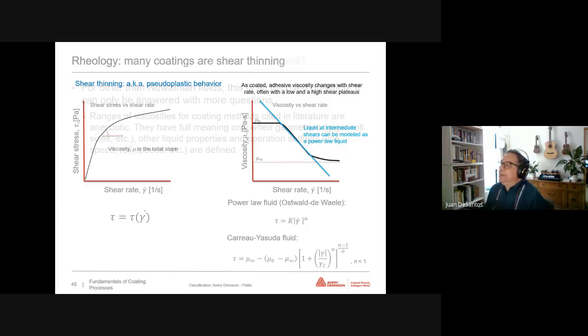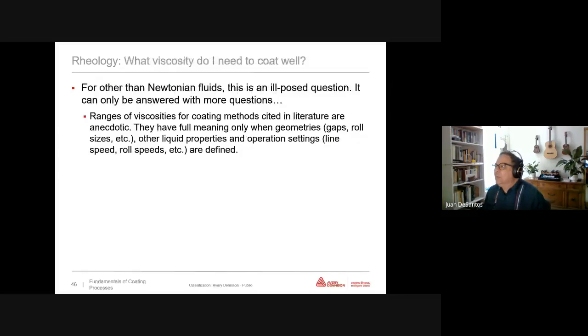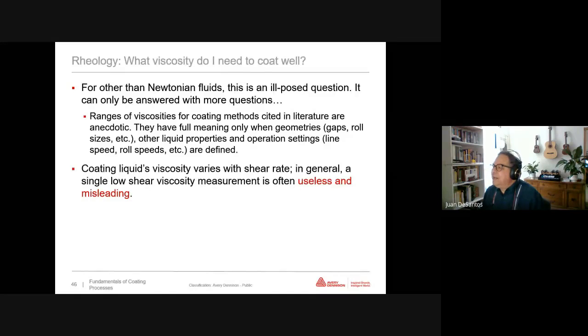Now, I often receive the question of what viscosity is needed to coat well. Well, as I showed you, the behavior is not that simple. And as you may guess now, this is an ill-posed question that can only be answered with more questions. You may find ranges of viscosities for coating methods cited in literature, but they are anecdotal. They have full meaning only when the geometry is well defined and other liquid properties and operation settings are defined. In general, coating liquid viscosity varies with shear rate, so a single low shear rate viscosity measurement is often useless and misleading.